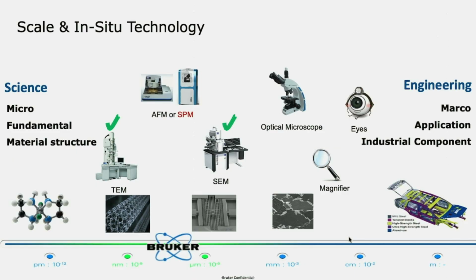If we don't have SEM, we still have the in situ technology we call the SPM or AFM. So in our company, we can use our nano indenter on the AFM. So we can use the AFM to scan the surface. We still can achieve nanoscale resolution of the surface. If you don't have AFM, we have a standalone nano indenter. We will provide in situ SPM. This is scanning probe microscope technology. Very similar to AFM, but we use our probe.